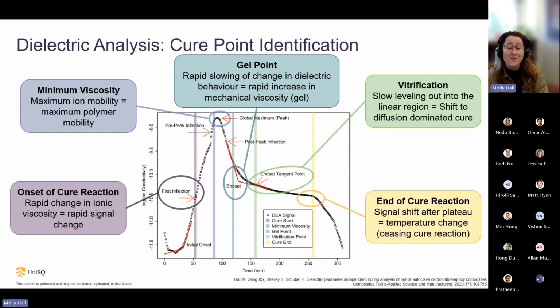cure profile of the oven has ended and the temperature has started to decrease, which is leading to a reduction in the signal. I want to make a clear distinction that we're not defining this as the completion of the cure reaction. Instead, this is the ending of the cure reaction because we are no longer putting in sufficient temperature to continue it. So what this really aligns to is when your reaction rate goes to 0. So we're not at fully 100% conversion, we're at the reaction rate has ceased.